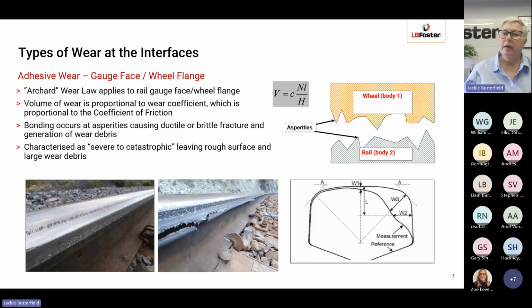But obviously the wheel and the rail are moving. So as the wheel moves, these asperities get ripped apart, ripped off, and they form wear debris. So what this does is leave a fairly rough surface behind and very large wear debris particles, which can actually be visible on the rail and on the foot of the rail and on the track. So this type of wear is characterized as being severe to catastrophic.